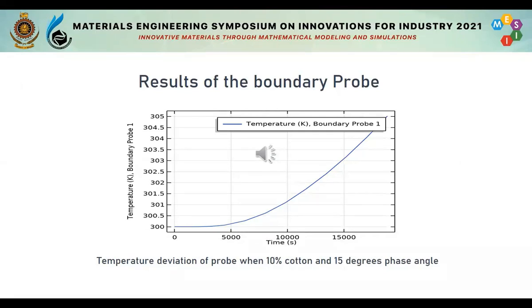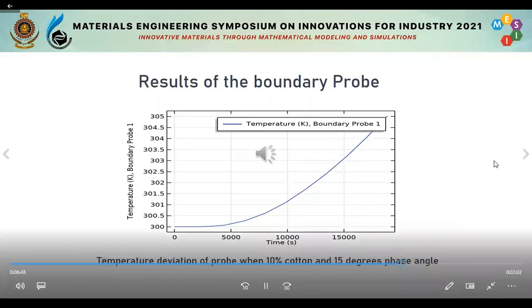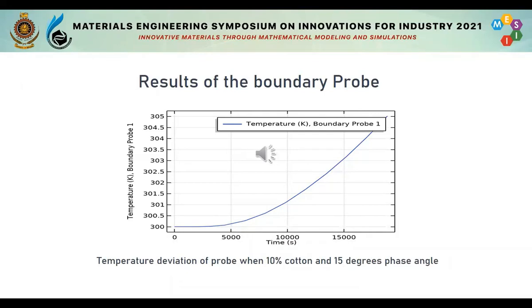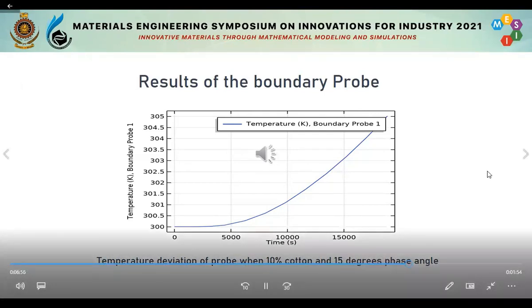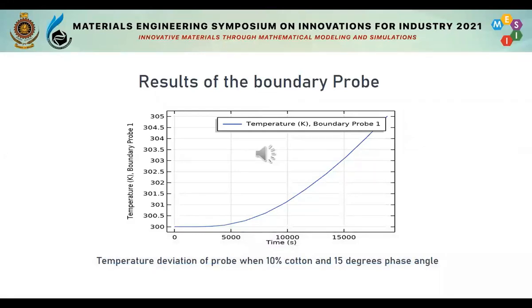So we generated these kinds of graphs for each percentage of cotton and LDPE. Considering the results of the boundary probe which is kept on the top surface, we could see that with time the top surface temperature has increased. So we generated these graphs for each and every percentage of cotton and LDPE, and finally we understood that when the cotton percentage increases, the time taken to increase the top surface temperature is also increased.